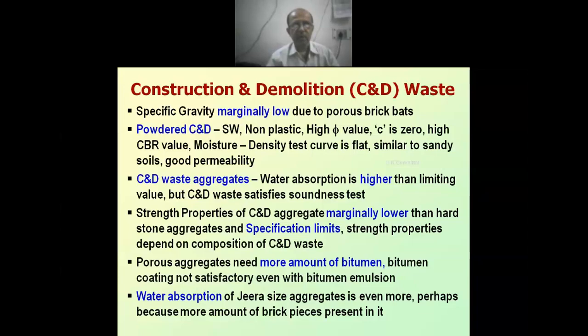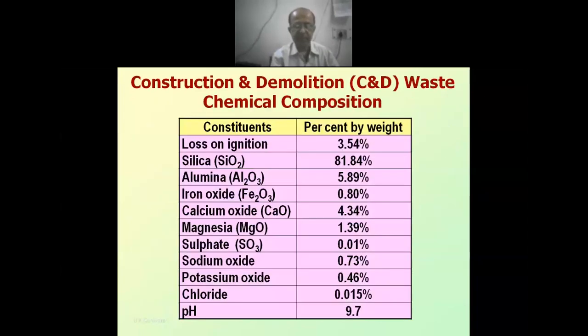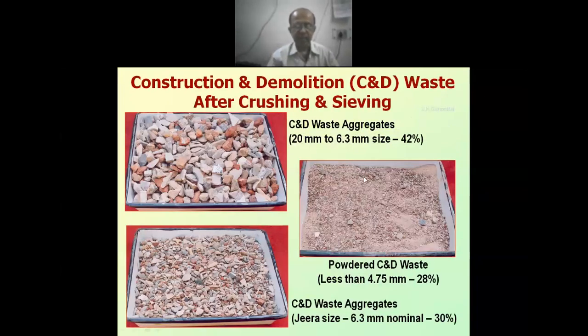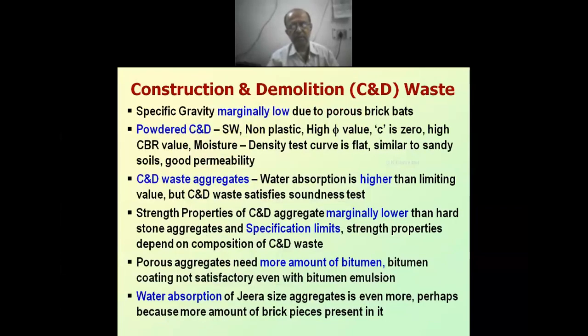It's non-plastic, high phi value, cohesion is almost zero, high CBR value. The moisture density test curve, that is the Proctor compaction test curve, is flat, similar to sandy soils, and it has good permeability. Powdered CND waste, this particular material, less than 4.75 mm size, was almost one third after crushing. When we did the sieve analysis and LL PI test, it was non-plastic. It was classified as a SW material, having a very high phi value. I will show you the strength properties table. And C was zero, cohesion almost zero, high CBR value, etc.